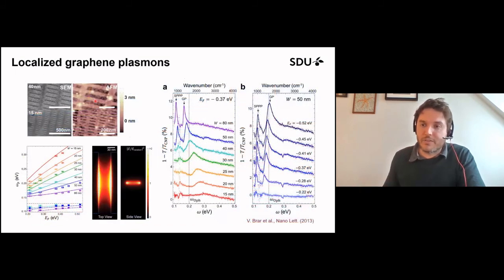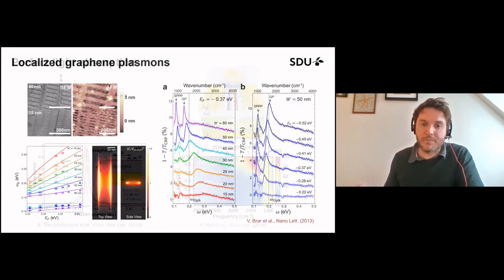Now, another strategy, rather than using this AFM tip, is to pattern the graphene into small resonators. Then you can have localized plasmons that don't propagate, but are standing waves that form in these particles of graphene, just like in the gold metal particle I mentioned earlier. And there you can tune the plasmon resonances by changing the geometry of the graphene, or also by changing the charge density in the layer, right?